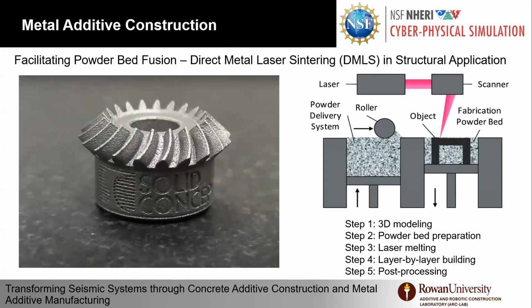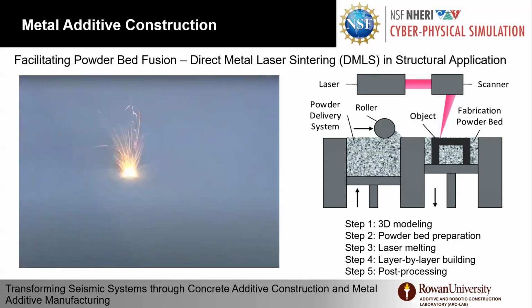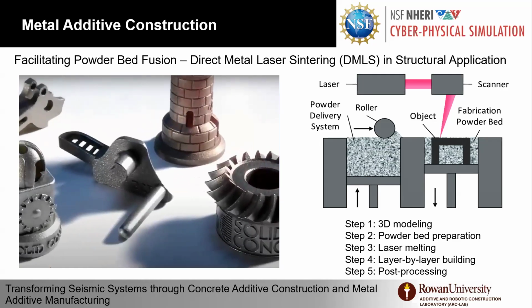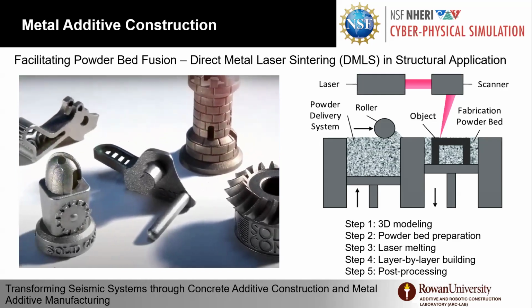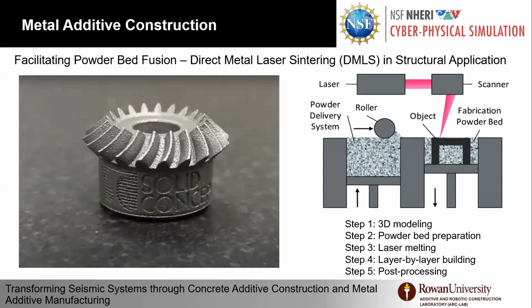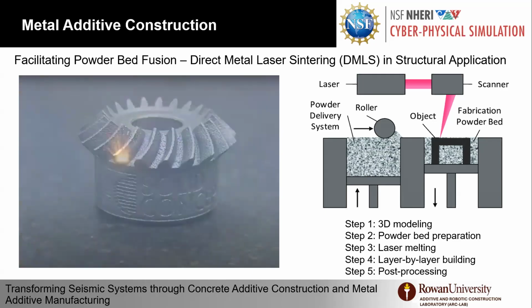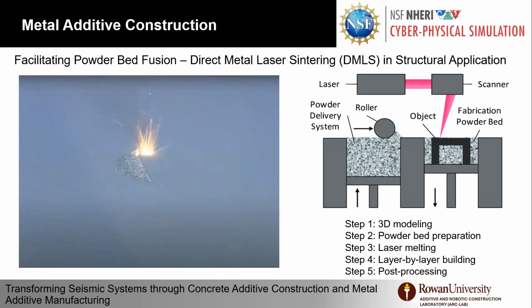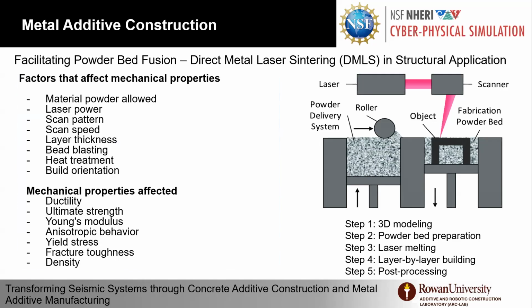So the technique here: we have 3D models, powder bed preparation, using a roller to slide the powder, using a laser for sintering and melting, and building layer by layer. The layer height in this technique is the particle size of the metal, so it's like 40 micron, and it may also require post-processing like heat treatment.